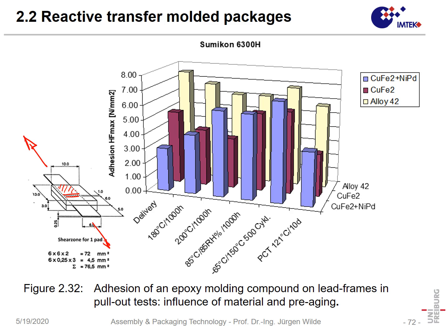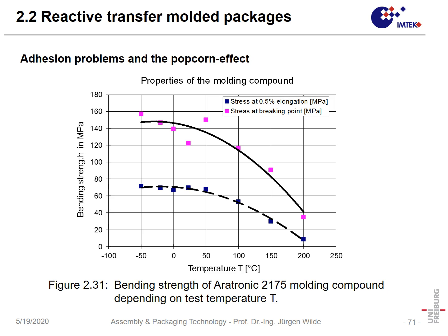These define the shear area. So at least that's half of the area. And when we go back, it's very interesting. The adhesion will be a result of this chemical reaction between the polymer and the metal. And on the other hand, it also will depend on the intrinsic strength of the molding compound. The strength of the molding compound is very high.